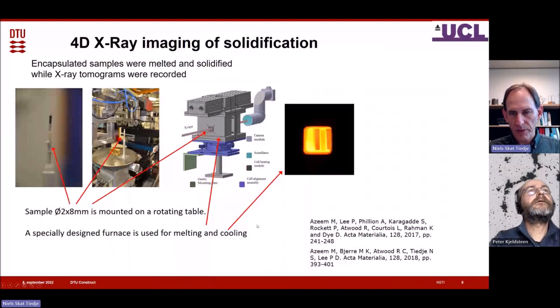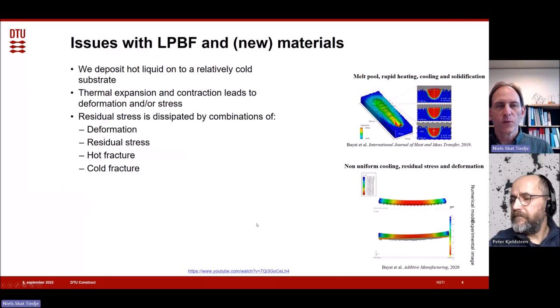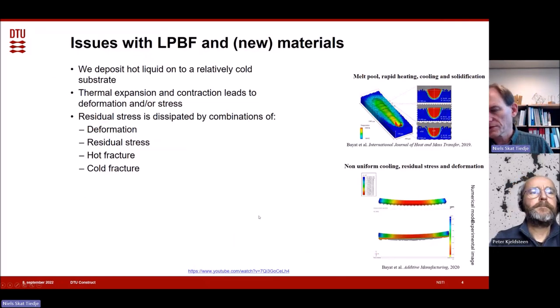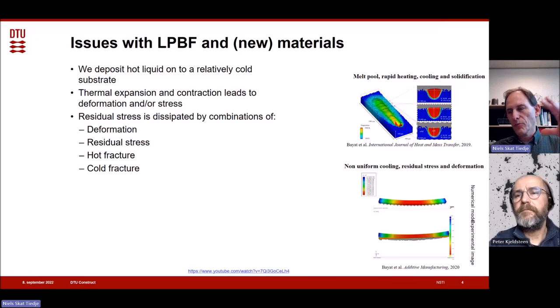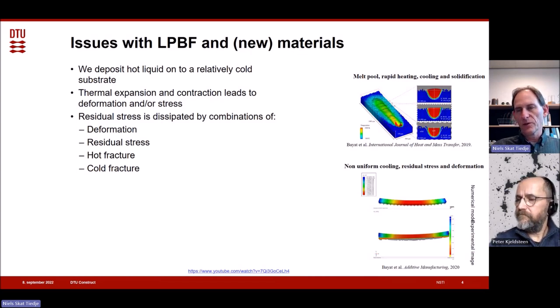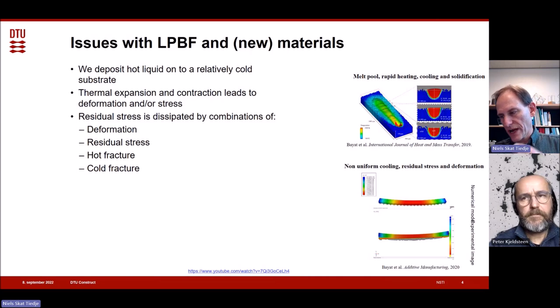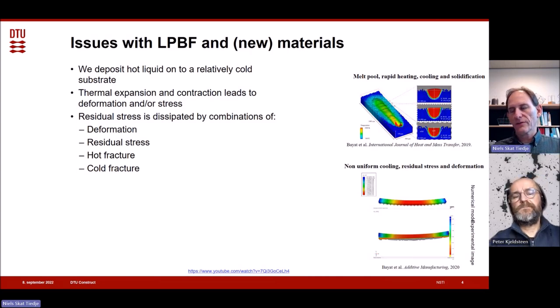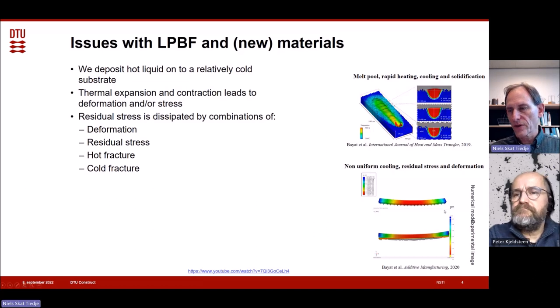Let me just share. This is actually from some slides I did recently in relation to work on laser powder bed fusion. Sorry, I have to scroll. But one of the issues when you have hot and cold materials, whether it's a mold with a cold surface and hot melt, is that it solidifies from the surface to the center. The bits that solidify first, of course, contract, and the bits that solidify later will stay liquid. But at the time where they solidify and contract, you have different thermal expansion and you get residual stresses in the material.